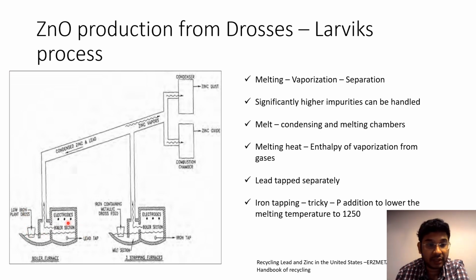You put a charge and then you have electrodes, you heat it up, and then you have the condensed zinc and lead flowing in one direction and the zinc vapors flowing in the other direction. Then of course it can go to the combustion chamber, which I explained before, can combine with oxygen, form zinc oxide, very simple reaction. Or it can be just condensed and then collected as zinc dust. Quite easy. The zinc recovery is taken care of here.